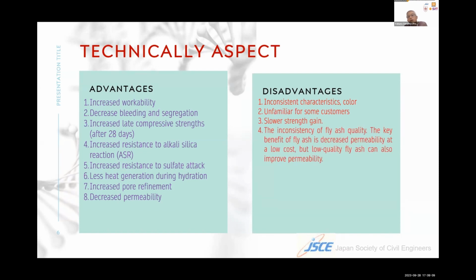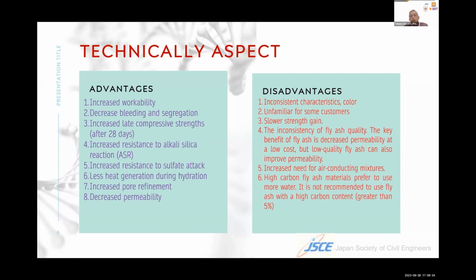So this is the disadvantage, the inconsistency of fly ash quality. The key benefit of fly ash is decreased permeability at a low cost. But low quality fly ash can also increase the permeability, or increase the need for air-entraining admixtures. And the sixth, high carbon fly ash material tends to use more water. It's not recommended to use fly ash with a high carbon content greater than 5%.